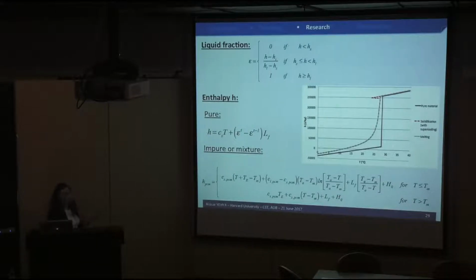However, from our experimental part, we can inversely infer what the enthalpy is, and we can prove that it's related to a certain number of impurities. So this is the enthalpy curve, which shows a progressive melting while a more direct solidification, and this is consistent with the heat fluxes from the experimental part. This part here is for the supercooling. We introduced a nucleation condition that doesn't allow us to go from this one to this part of the curve